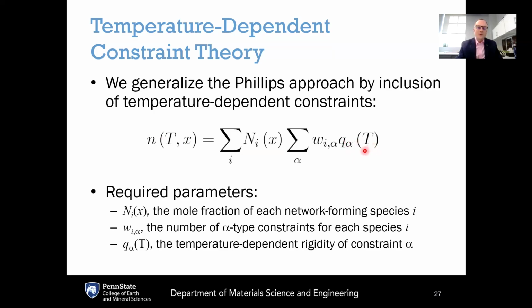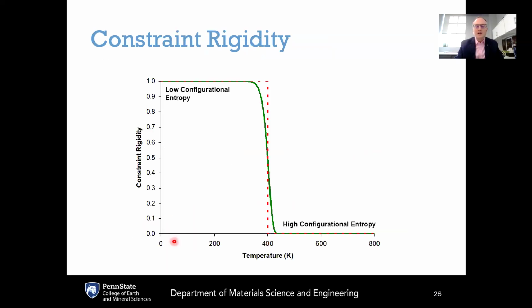So the parameters that we need to use this theory are the mole fraction of each network forming species. We get that from our statistical mechanics section that we just finished. This follows a non-central hypergeometric distribution as we described. The total number of the alpha type constraints for each species i, and then the temperature-dependent constraint function. That temperature-dependent constraint function looks like this.